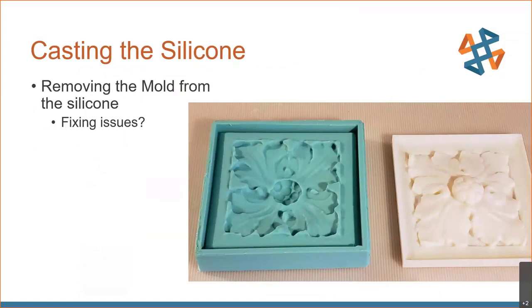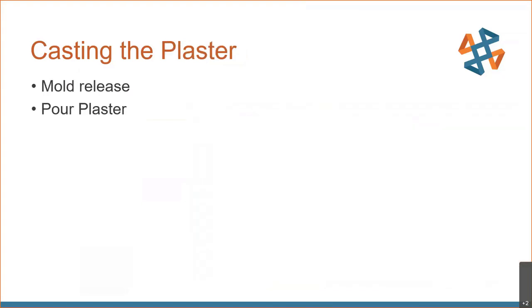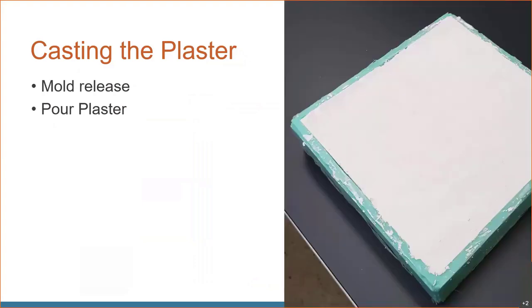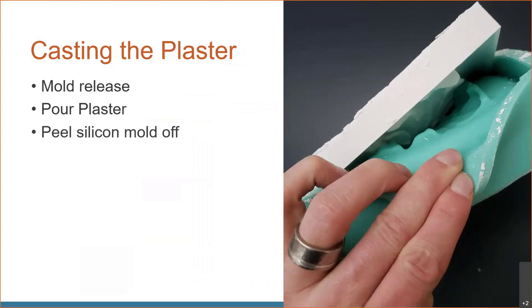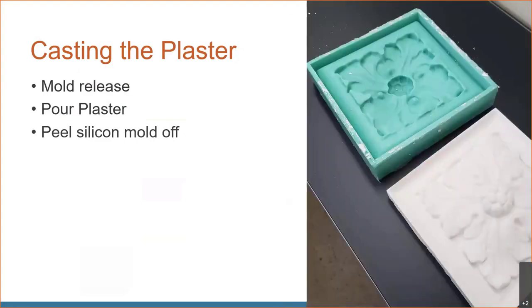The silicone mold turned out great with no issues needing correction. Now we have a fully ready-to-use silicone cast — essentially the same end result we achieved with the rubber printed mold, but here achieved via silicone cast off the rigid master. We then cast our plaster directly into the silicone mold, let it cure, and peeled it off extremely easily with the Shore 15 very flexible mold — giving us our plaster recreation.